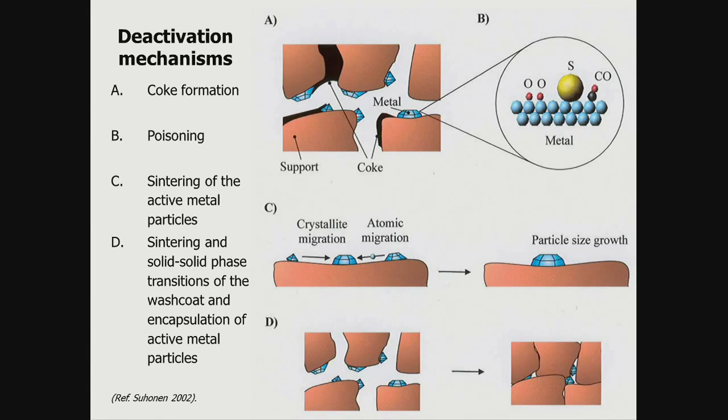So you're saying to yourselves, well, surely we don't design processes to do this. Surely we try to stop it. Fluid catalytic cracking. I'm an FCC man. It should at least begin the lecture and it should at least end the lecture if I'm doing my job right. FCC, fluidized bed, cat cracking, making carbon, deactivates the catalyst within 15 milliseconds, 15 to 100 milliseconds. Catalyst goes into a 5-meter riser tube, about half a meter, maybe 3/4 of a meter in diameter. Feed goes in, catalyst goes in, it gets to the top and it's dead.